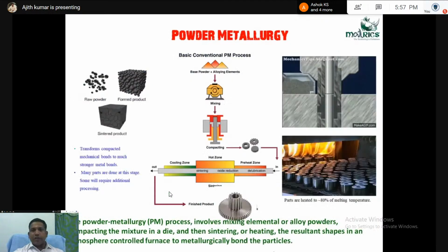Another important metal processing technique is powder metallurgy. This is a solid state route. Metal casting is a liquid state kind of processing. Powder metallurgy is a solid state processing method. In the process, we have metal powders or metal lumps, or metal with ceramic lumps to make a composite. First we mix using ball milling or some mixing machine. We mix the sample powder. Then we put that powder into the mold and do compacting. After compacting, that part or sample is put through sintering. After sintering, we get the finished product.